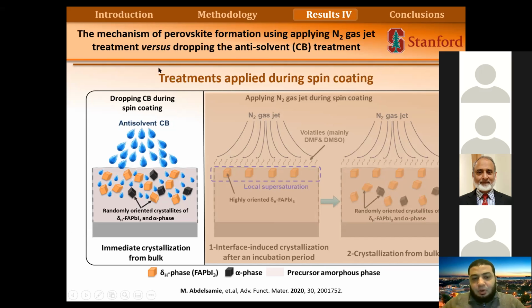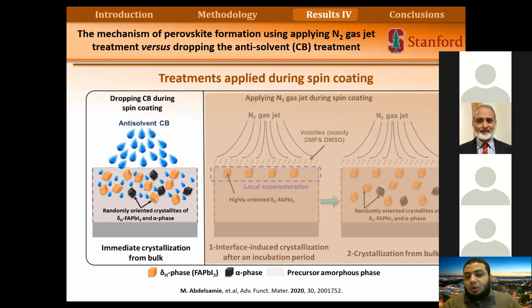For example, dropping anti-solvent and applying nitrogen drying. These methodologies were published earlier, before I did my work, by NREL. They investigated these techniques and the stability of the cesium FA. They found that when you use mixed cations like cesium FA or add MA, you get more stability. Just for cesium FA, it was stable for a month and then decayed.